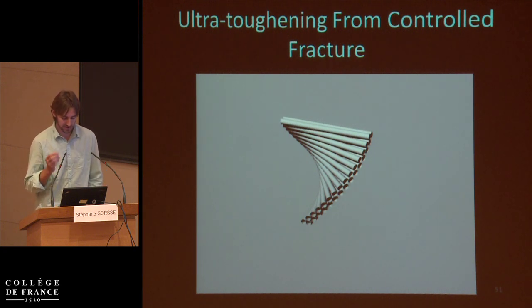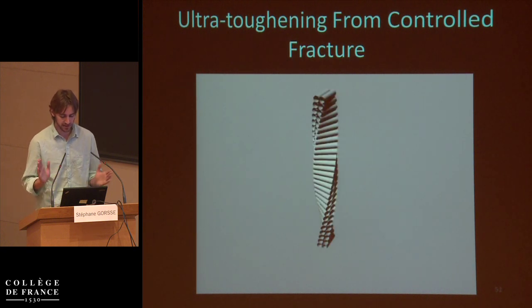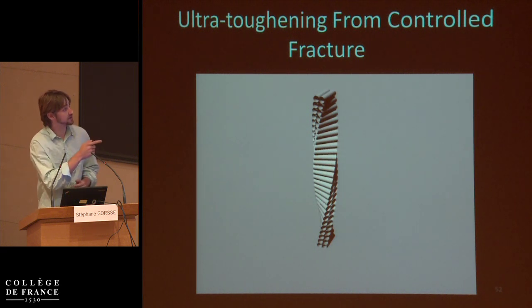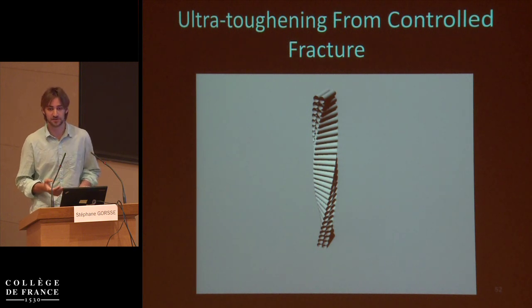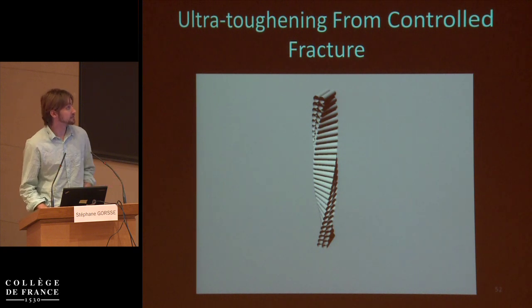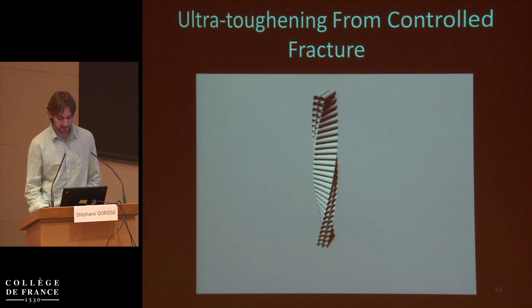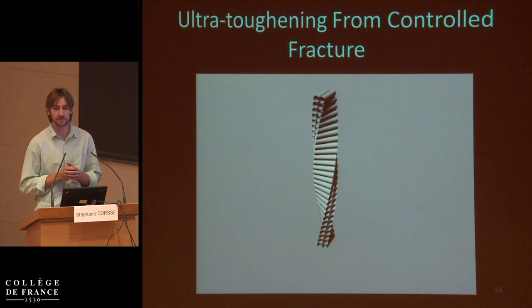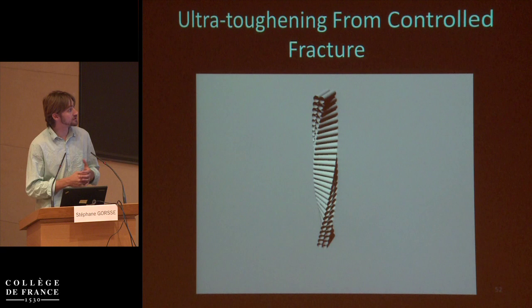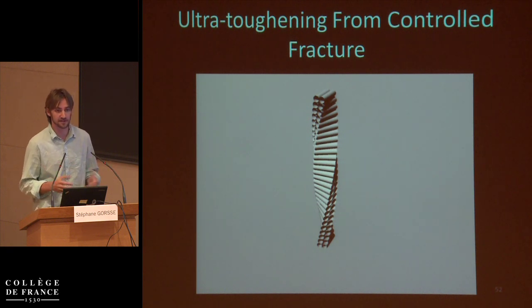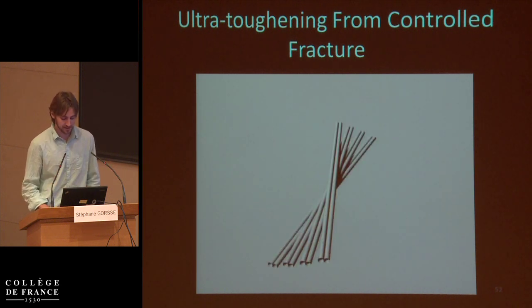But now we can consider each of the ways that this helicoid can grow individually. So let's constrain the radial direction and just consider the longitudinal direction. What we have here, if there was a fracture in the middle here, that's basically the pore channel. So the material begins loaded with fractures, is a way to think of that. But that's not a problem, because this is just little hairs. None of these are catastrophic. None of them are propagating through the material such that they cleave the material in half and create catastrophe.